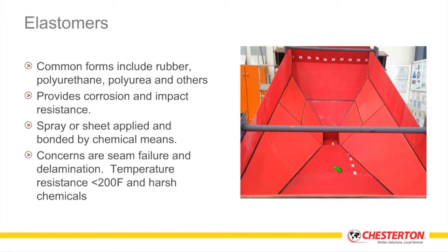Another category of lining systems that are commonly used would be categorized as elastomerics. These systems can include your natural rubbers, your polyurethanes, your polyureas. They're chosen typically first and foremost for their impact resistance, and depending upon the formulation and chemistry, you can get varying degrees of corrosion and temperature resistance. These materials are normally applied in a calendared sheet format. If it's a sheet rubber lining system, an adhesive is laid down, the rubber is pressed out onto that flat surface. The seams are sealed with typically an overlapping seam layer, and that becomes your liner.